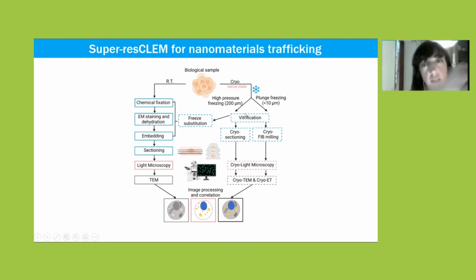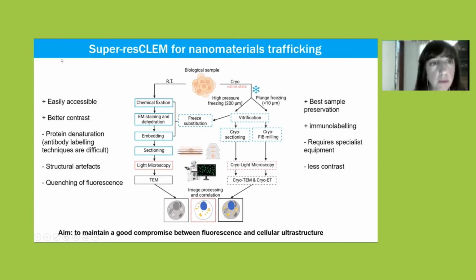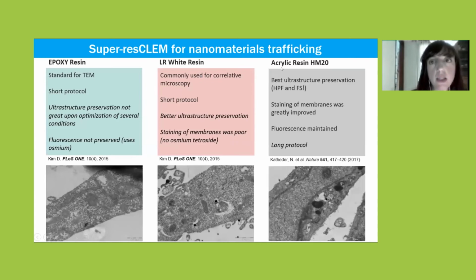Okay, so we discarded the totally cryo method because for us it was too complicated, but we wanted to compare between the standard techniques and the freeze substitution. So I can skip. So we tried epoxy resin, LR White resin, and then the acrylic resin with high pressure freezing and freeze substitution. And analyzing the ultrastructure, we saw how freeze substitution was for us the best method, and also, despite being the longest protocol, because these two are much faster, we chose that one not only because the ultrastructure was greater, but also because the fluorescence could be maintained, because in these two, mostly osmium is used, so it kills quite a lot of fluorescence.